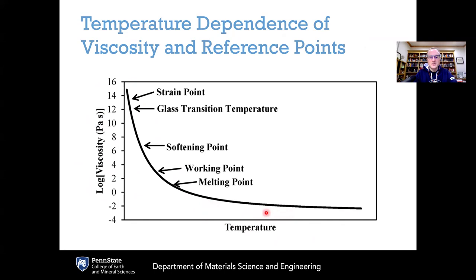Within the industry, there are viscosity reference points defined on the viscosity versus temperature curve. The y-axis shows the base 10 logarithm of viscosity in pascal seconds as a function of temperature. Starting at high temperature, the viscosity is very low, around 10 to the minus 2 pascal seconds, but as you cool the system down, the viscosity increases by orders of magnitude. To make comparisons between compositions, a set of viscosity reference points is defined: the melting point, the working point, the softening point, the glass transition temperature (also known as the annealing point), and the strain point.